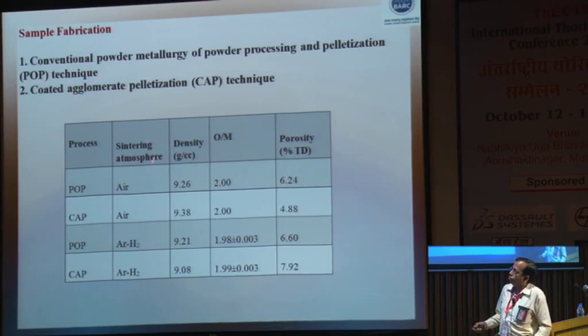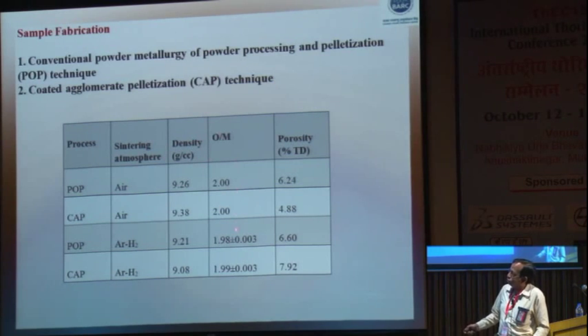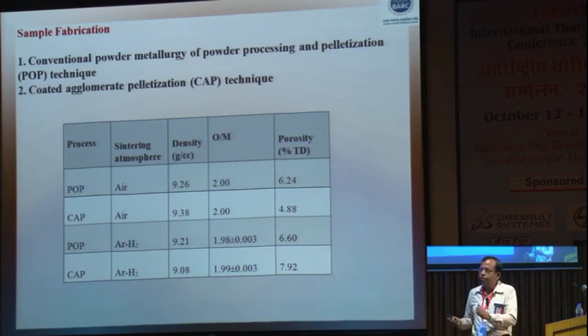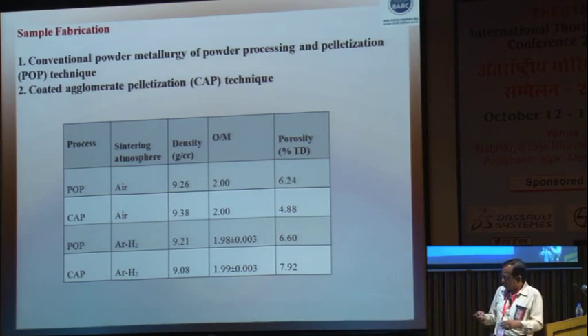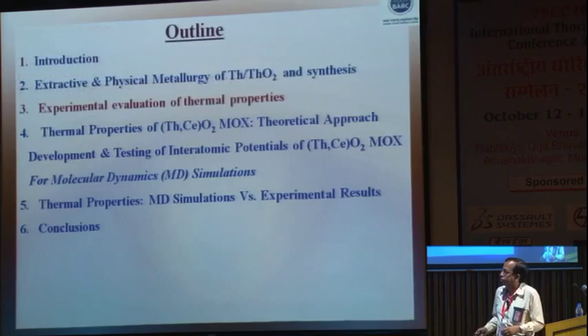Just to give you a flavor of this activity, the sintering atmospheres have been changed, both for POP as well as CAP. We have used air as well as a mixture of argon and hydrogen, and you can see the O by M ratios are more or less the same by both the processes, but the density and the porosity contents differ, and this leads to change in thermophysical properties. When you measure them, you can see that there are minor differences which could be important.